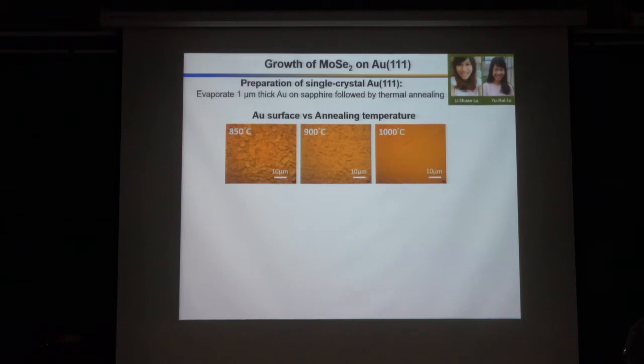So you already know the key. The key is the gold, not the MoSe2, right? So we also deposit a thick layer of gold on sapphire, followed by thermal annealing. If you use a lower annealing temperature, you can see very porous grain. Up to 1,000 degrees C, you can see the crystallinity become much better.